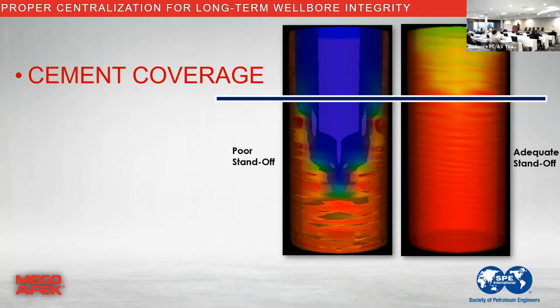But you may have one side of your liner fully covered or over covered, and the other side may not necessarily be covered. So if you look at this simulation here, aside from the diffusivity of the fluids that causes the change in color, on the left side, it seems like if that were a liner, if that were a shot from one of the angles of the 360 degree circumference, you see that one side did not make it to where it's supposed to. On the other side, no issues, because we had a fully engineered slurry design, and diffusivity was not that bad. Flow regimes were great. So you got full coverage. Everybody's happy.